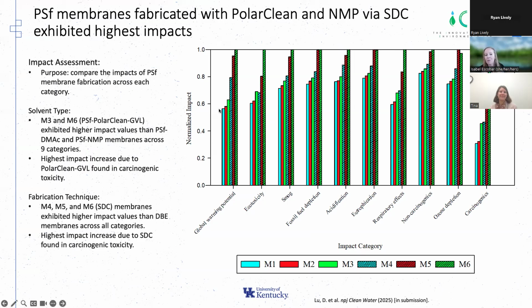When we were talking about just separating out the doctor blade only, the impacts were not as significant, though they were higher for the green solvents. When we went to the slot die coating, we saw that just by using slot die coating, all of the impacts were higher. Again, we have to have some sacrificial dope solution to reach steady state, which we don't at the doctor blade level. The slot die coater does use power, and it produces a greater amount of waste than we do at the doctor blade level.